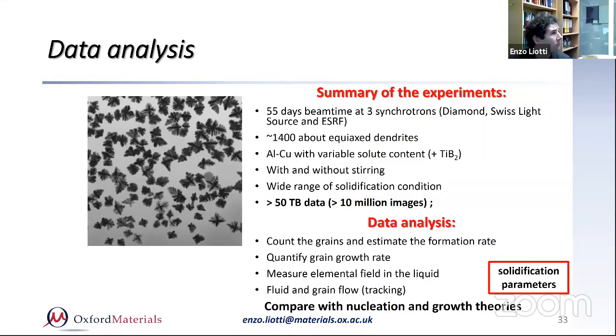And if you got all this information, we could compare them with nucleation and growth theory and test their validity, and also do that as a function of all the solidification parameters. However, if we have to do it by hand, even just the counting would imply that we basically spend our days putting dots on a screen, because a typical experiment has maybe 200 or 300 frames that are the useful range in which you start to see grain until the solidification is finished. And that means that if I want the nucleation rate, I should go in each frame and count the grain, so put in dots.